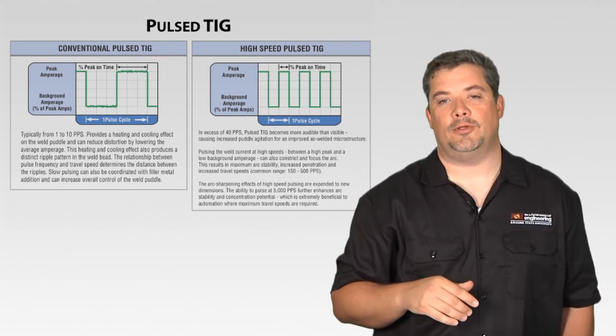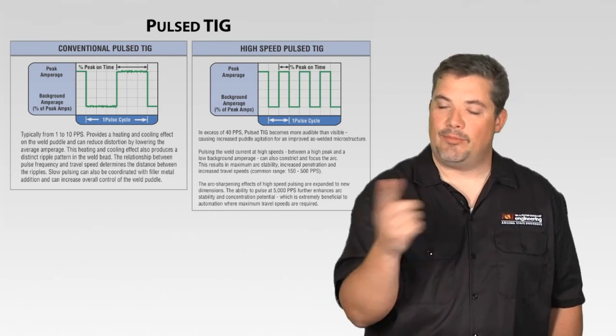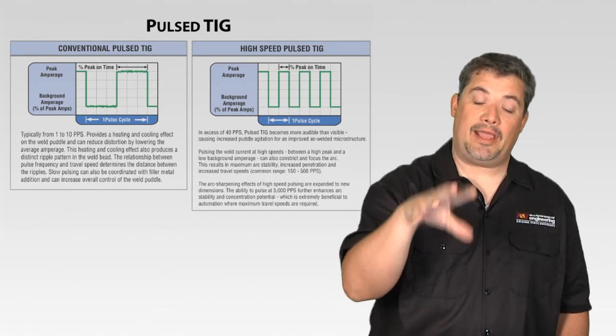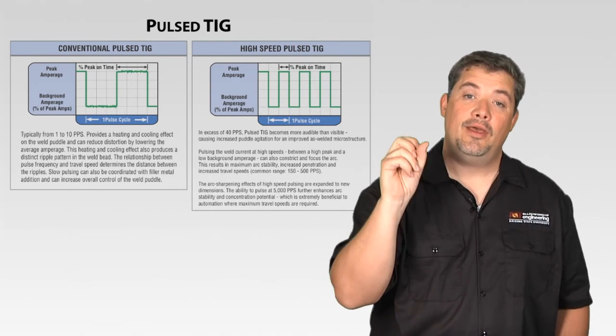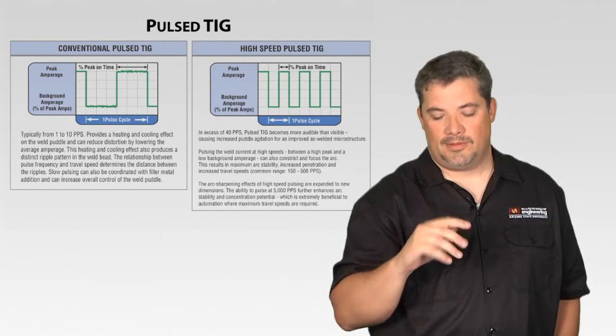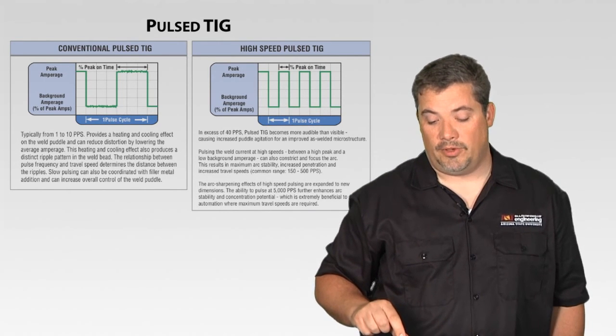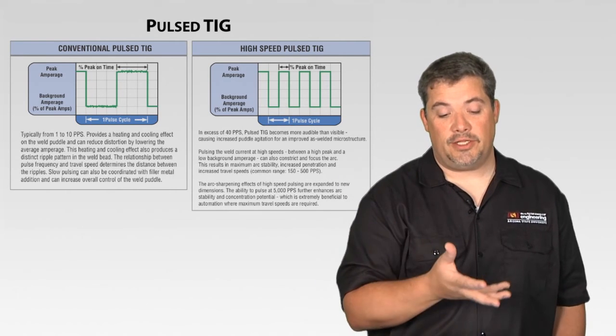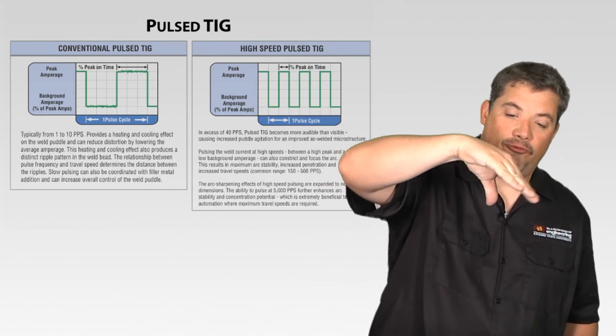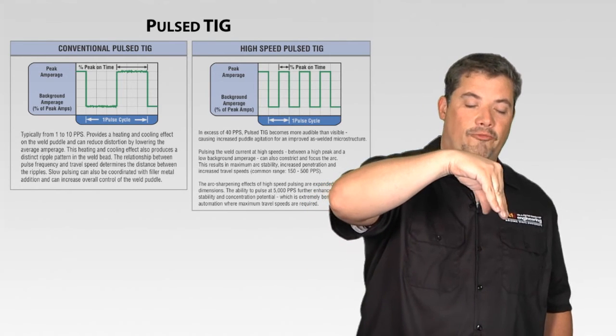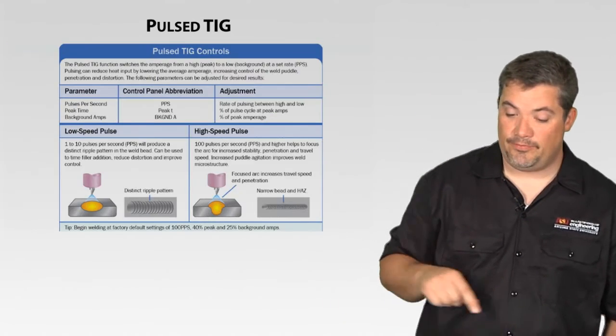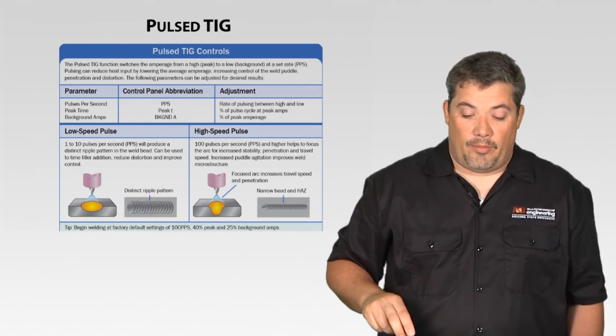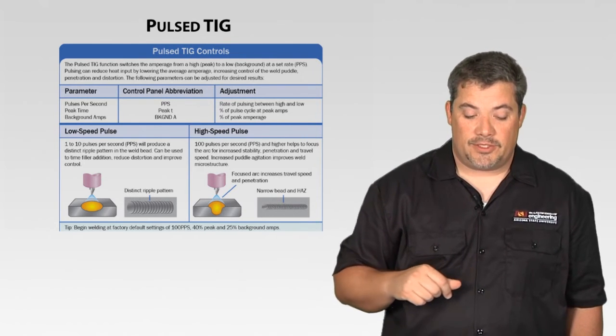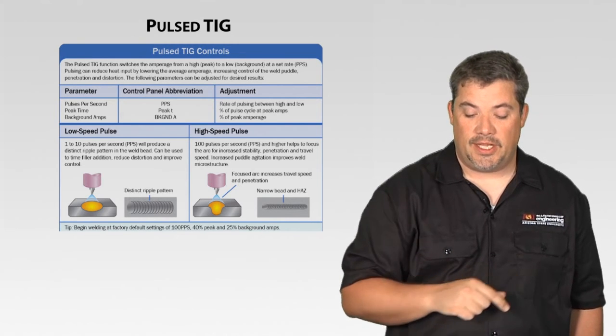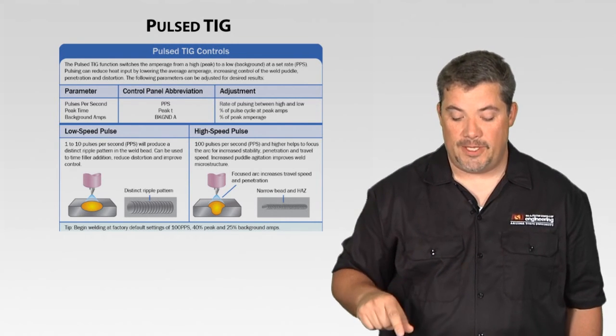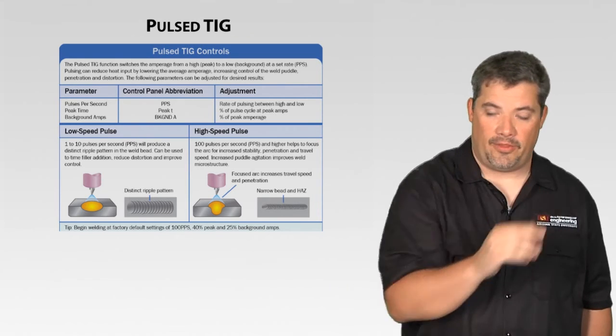But those lower pulses per second, I can actually see it flickering. Same with those AC hertz, that 20 AC hertz, I can actually see that there's an on-off thing happening between the positive and negative polarity. So at the higher frequencies, it's audible, not visible. Again, changing the pulse frequency changes how focused that arc bead is. Higher hertz, more focused; lower hertz, less focused. The pulse TIG controls, again, we don't need to cover this too much, but low speed pulse, you get distinct ripples. High speed pulse, you get narrow beads, a lot tighter together.